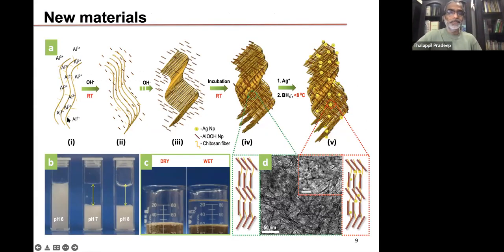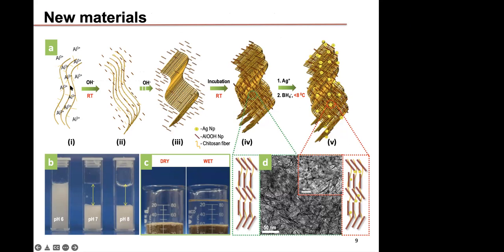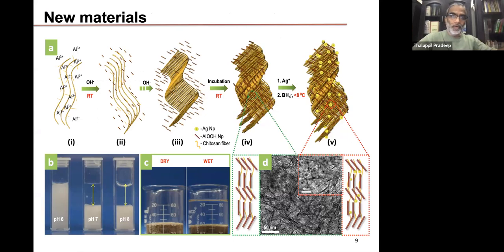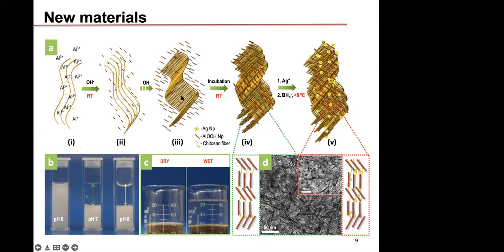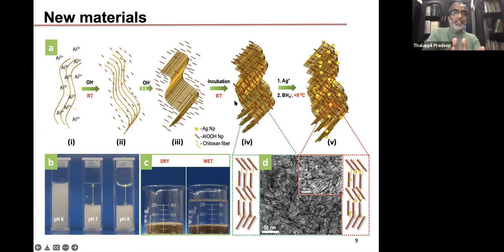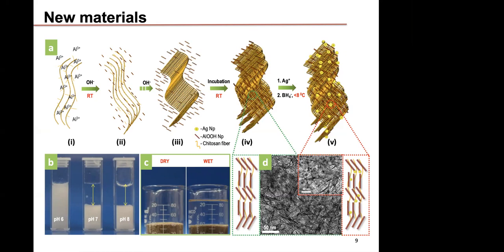We take biopolymers. There are a number of biopolymers that one can use, including cellulose or chitosan. Several biopolymers. On these biopolymers, we crystallize aluminum oxyhydroxide in the form of nanoscale flakes. And on these biopolymer templates, when you crystallize such materials, it is possible to create nanoscale cavities. In these cavities, you can trap nanoparticles and you can design such nanoparticles in cavities.